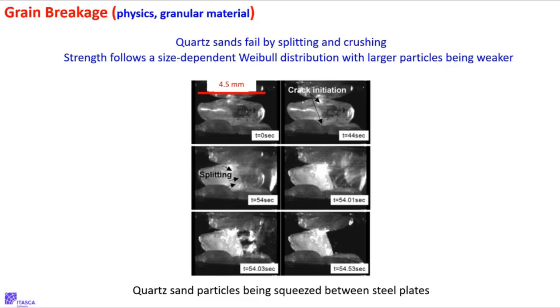Why are they weaker? Well, people can postulate that the reason this thing finally fails is that there's some kind of critical flaw in here that gets triggered. And if I have a bigger sample, I'm more likely to have a critical flaw, and so I'm going to fail earlier. That's why people talk about larger things being weaker. Okay. And actually the Weibull distribution can be shown if you make a simple theoretical model of a micro thing that instantly causes rupture. You can show that it should follow a Weibull distribution. So key thing, bigger grains are weaker.